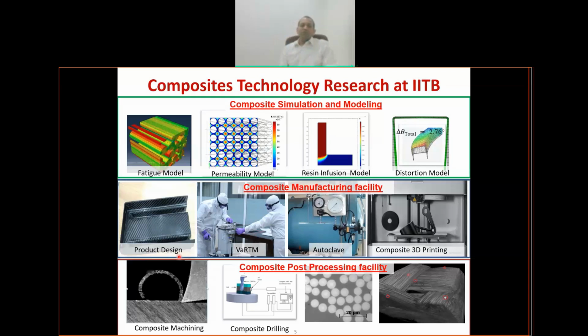When you go through the curing process of a composite, the curing results in shrinkage of the resin, and that distorts the material. As a matter of fact, the first Dreamliner, when they were trying to fit the fuselage along with the front part of the plane, they realized that the two were made at two separate places, and these were huge, of course, cylinders. They were trying to fit it together, and they realized because of distortion, there was almost a 2 inch gap, and thus they could not fit. And that was a huge challenge, and that delayed the Dreamliner process for a while. Of course, they were able to get over it, and they were able to create composites which were matching up to millimeters, so that they could be put together.